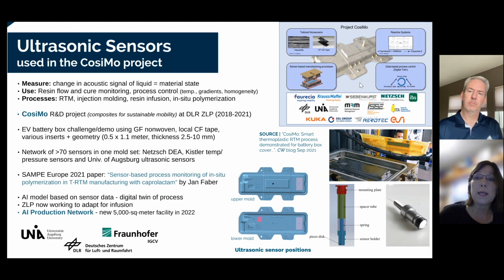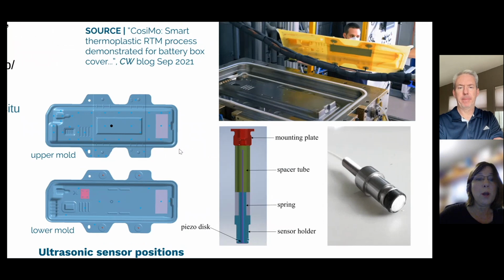It's a different process. It is what we call thermoplastic RTM. So they took a caprolactam monomer and they polymerized that in situ during the RTM to become PA6. So that's nylon 6, and that's the part you end up with. So obviously, it's really important to, number one, make sure that you know that that monomer got into all the crevices and the different geometries. So if you see here, this is the sensor grid on the upper mold and the sensor grid on the lower mold just for the ultrasonic sensors. And that lets you see what's going on at every different part, right? Where the resin is going and how it's polymerizing.